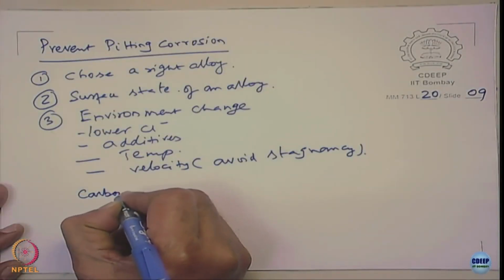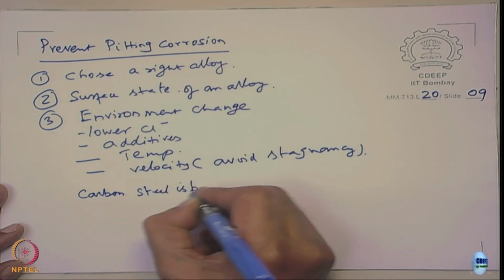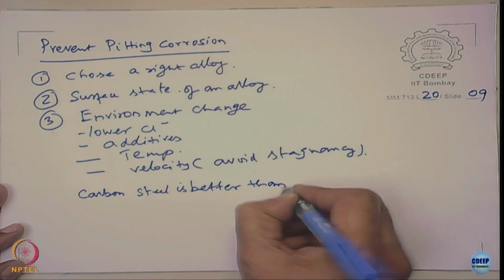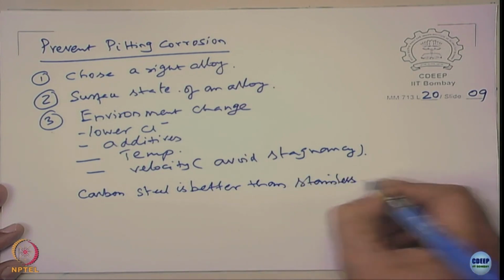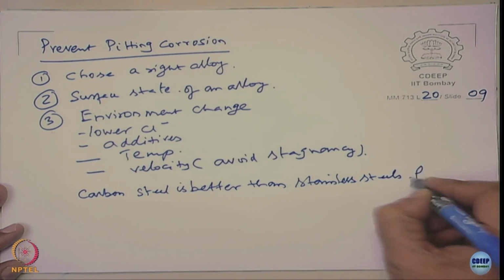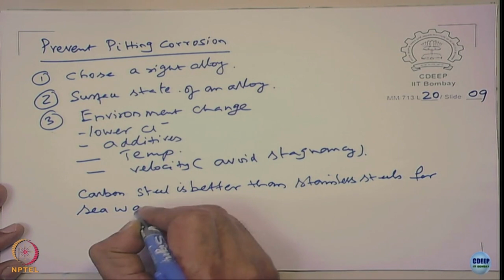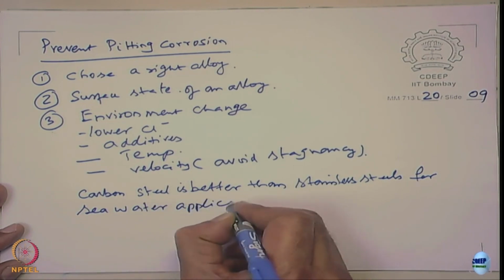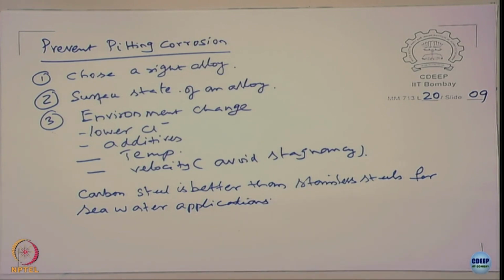But the other way of looking at it is you choose an alloy which is not passivating. For example, carbon steel is better than stainless steels for seawater applications, right. That is why a ship hull is made up of what? Made up of carbon steels, right, not a stainless steel. But what is the problem with carbon steels? The uniform corrosion rate is more, right. The uniform corrosion rate is more than that of the stainless steels.